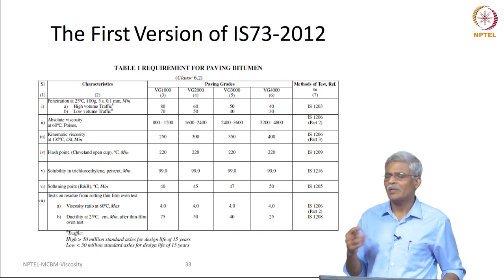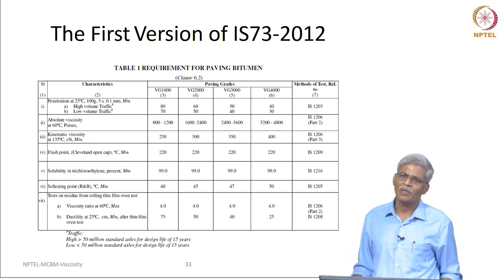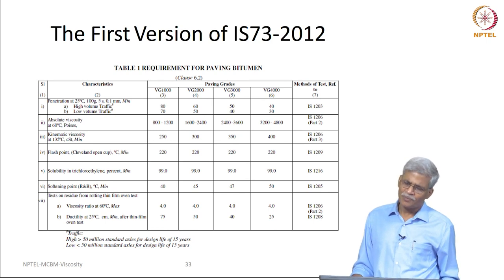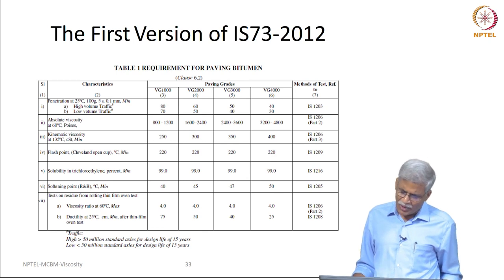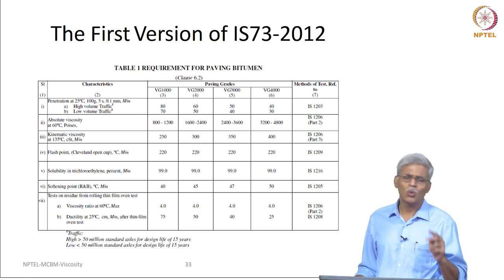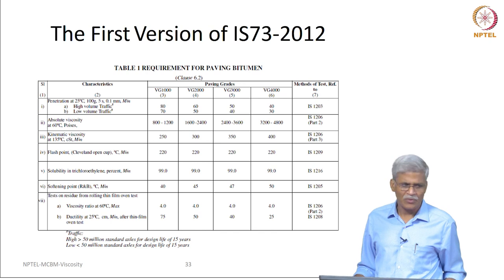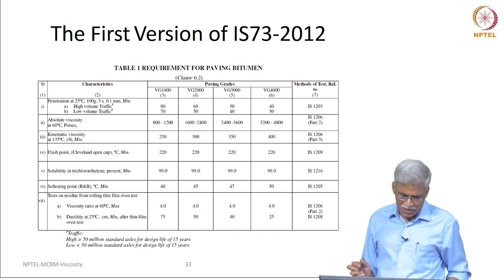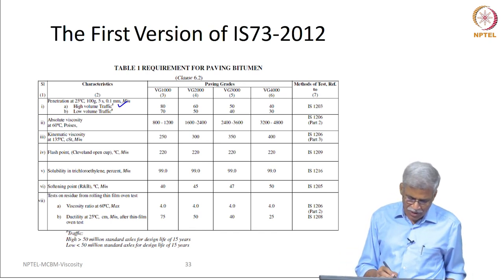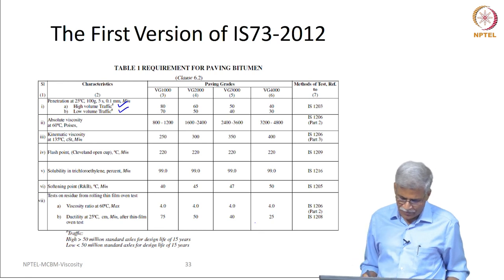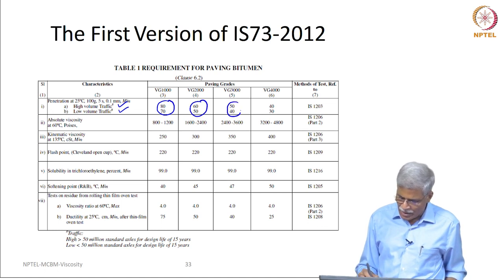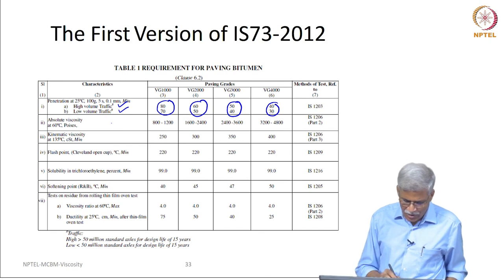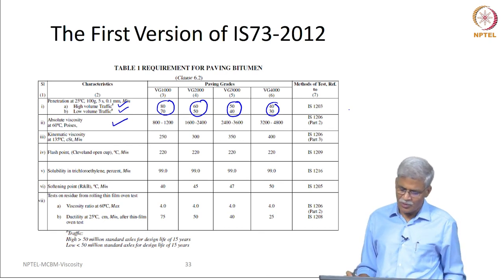Because there is considerable pavement engineering and pavement design background needed, originally we came out with two sets of classification. The first classification is based on high volume traffic and low volume traffic. We kept the penetration values different for high and low volume traffic, but we kept the viscosity constant irrespective of traffic level.